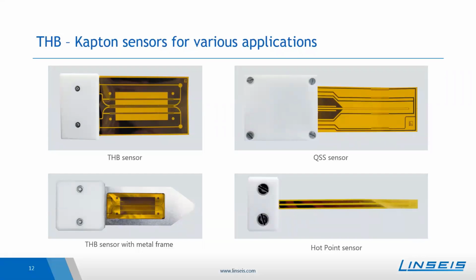Also, there was a question regarding the degradation of the sensors, so how many times the sensor can be used. So the sensors are very durable, so one can use them for a very long time, but this depends also on the application. So for high temperature applications, the lifetime, of course, shortens. So the THB sensors, as already mentioned, can measure up to 200 degrees Celsius.